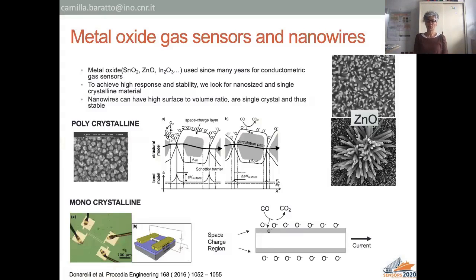Metal oxides are known since decades to be effective for gas sensing application. In the past, they were used as polycrystalline gas sensors, where the material was deposited as thin or thick film, and the interaction of the gas with the surface of the semiconductors is working with the grain. What is important is the grain size, and to have nanometric grain size is of great importance. The problem could be the coalescence of the grain due to high temperature operation. And this problem can be overcome by using